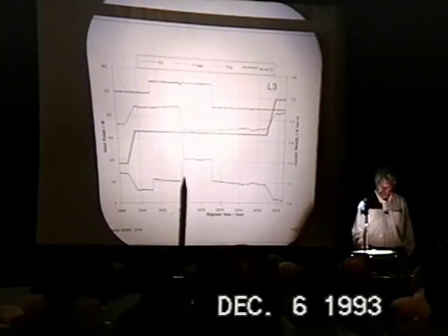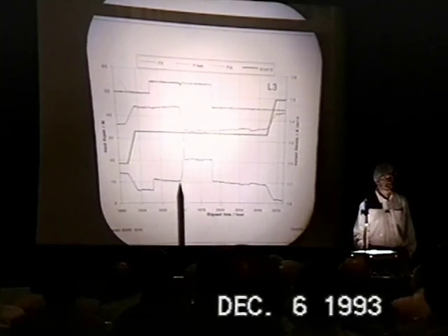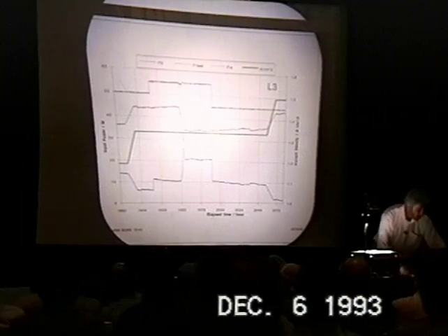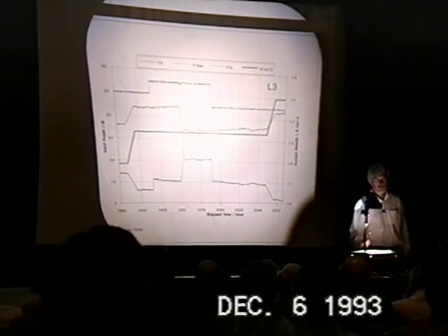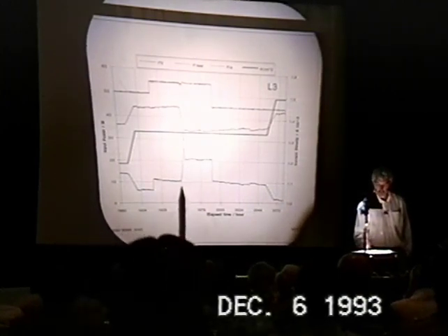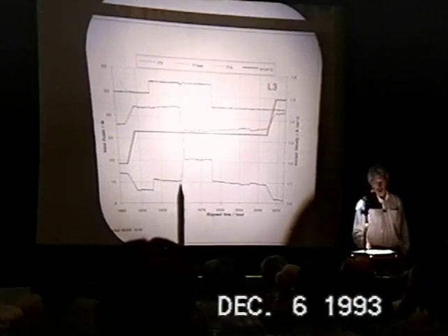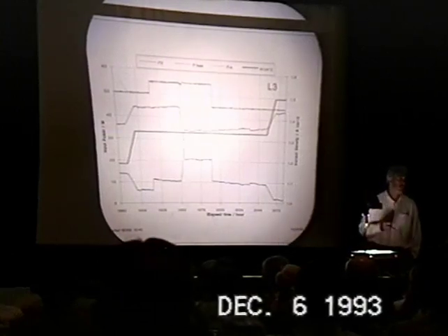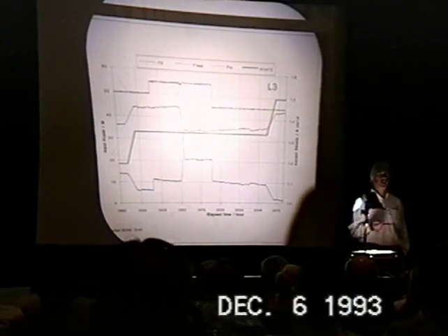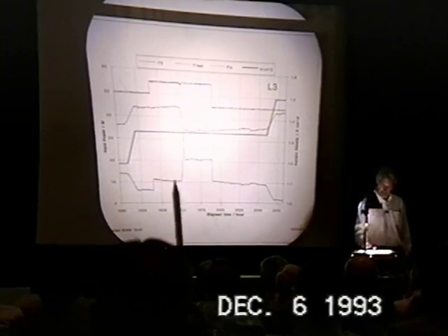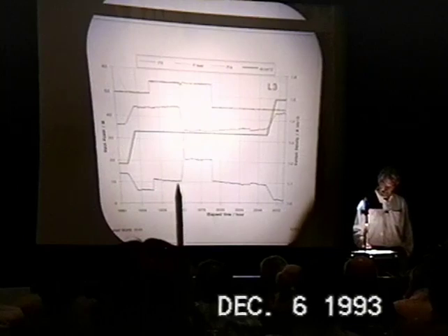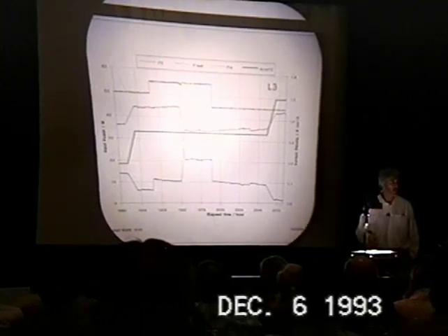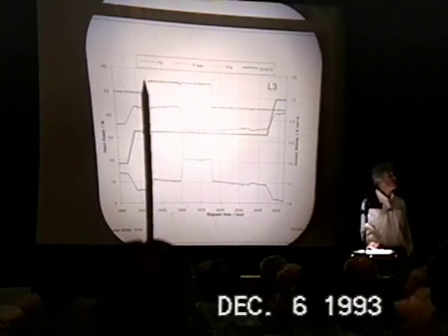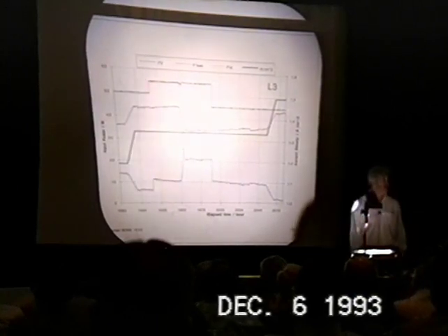At this point, something that we had not planned occurred, and happens in many cases. It taught us something that we, I think, might very well be important. The inlet flow was blocked by a small piece of black plastic which happened to be floating in the bath for reasons which I won't go into, so that the mass flow decreased. The system was putting in 60 watts, but now the rate of cooling was reduced.